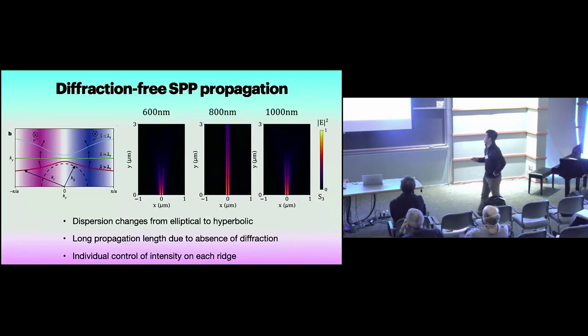So you form this periodic, alternating structure. So you can engineer a hyperbolic dispersion that's dependent on the wavelength. When the wavelength is small, you can have this hyperbolic dispersion, and when the wavelength is large, it turns to this normal elliptical dispersion. And there is this transition frequency where the dispersion is flat. So this means that all of the group velocity will be pointing upwards.